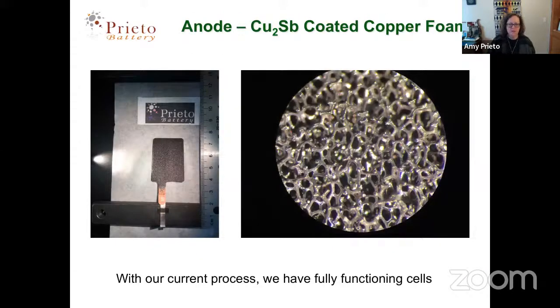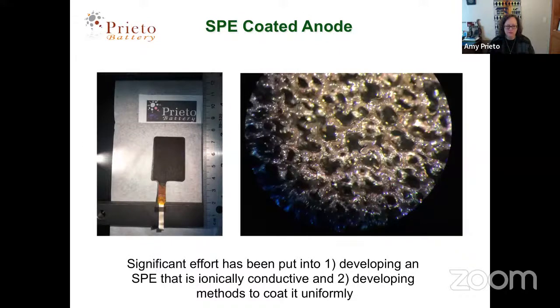So some optical images now showing you some of the optimized cells that the company makes. This is an image on the left showing you our ultrasonically welded tab. That's where we're going to make contact for the electroplating, but then at the end, when the battery is packaged, that is the tab for the anode. And the image on the right shows you the copper antimonide really coating the foam pretty uniformly. It coats throughout the thickness of the foam. And in the company, we have spent quite a bit of time developing really good tools to be able to manage very high quality, high fidelity electroplating in very short amounts of time. This is what the cell looks like when it's coated with the polymer.